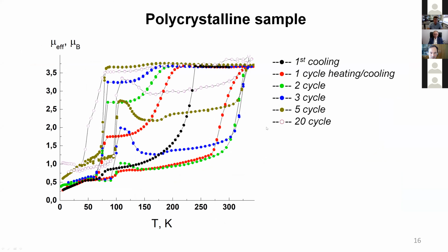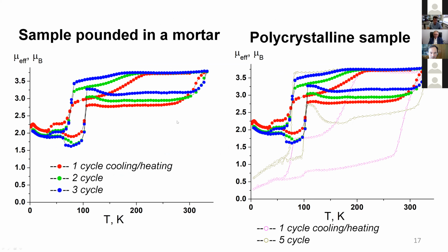During the repetition of the cooling-heating cycles, irreversible changes in magnetic properties occur. After 20 cycles, hysteresis clearly manifested in the low temperature region. If the initial polycrystalline sample is ground in a mortar, the dependence of the magnetic moment is relatively close to that for the polycrystalline sample after repeated cooling-heating cycles several times. The main difference is the value at low temperatures. This value corresponds to a content of non-interacting paramagnetic centers of about 30%.